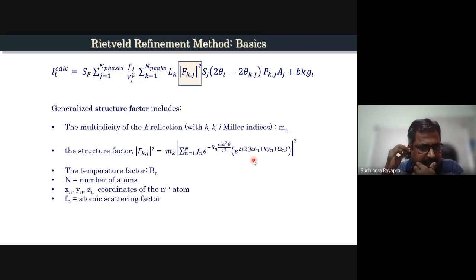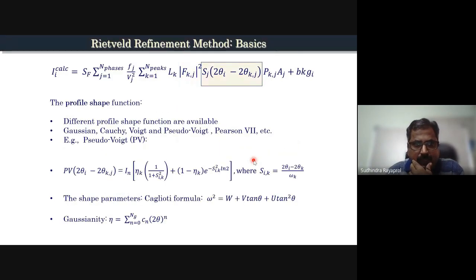Okay, so based on the information which we provide, based on the number of atoms, what type of species of atoms there are, what are these crystallographic conditions like space group and positions, it will scatter and generate the Bragg peaks according to that structure factor. Other is the shape function. So for different diffractometers, whether X-ray or neutrons, you have a peak shape function, right? It can be Gaussian, pseudo-Voigt, Cauchy, Pearson, and so on, depending upon the electronics and the arrangement of that instrument.